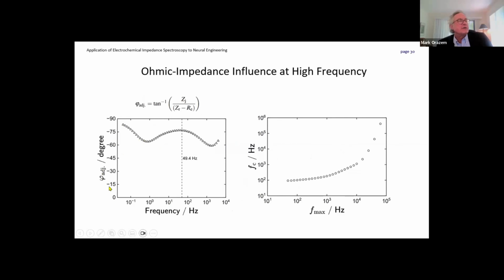This is showing you the phase angle as a function of frequency. And you're seeing something very similar to what I showed you for the oxide on steel, this little bit of a dip over here. And a characteristic frequency for this data set was around 50 hertz. What we found, and this region over here is the part that's influenced by the ohmic impedance.